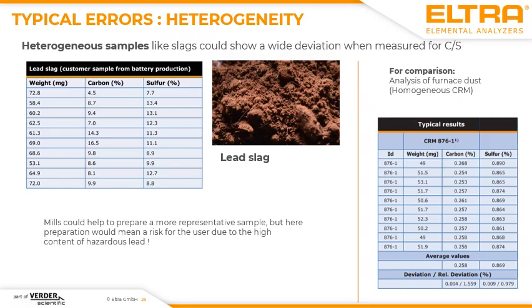But maybe a more, I would say, correct analysis is required as, for example, for the comparison results which are listed on the right side. There we analyzed furnace dust, which is also finely divided powder with comparable sample weights, but here we have very stable results even in the low concentration range. So when you are faced with heterogeneous samples, think about, should I spend more energy on the sample and prepare a more homogeneous sample, for example with ball mills, or can I accept the results we are facing here?